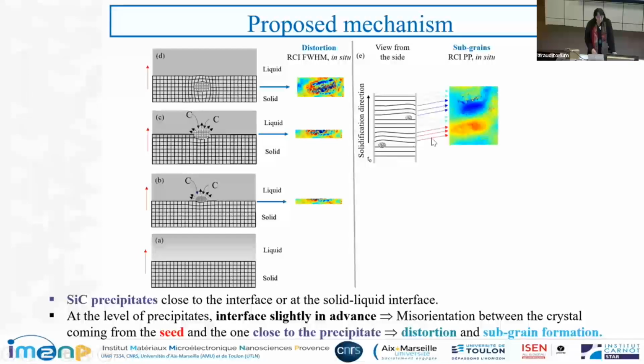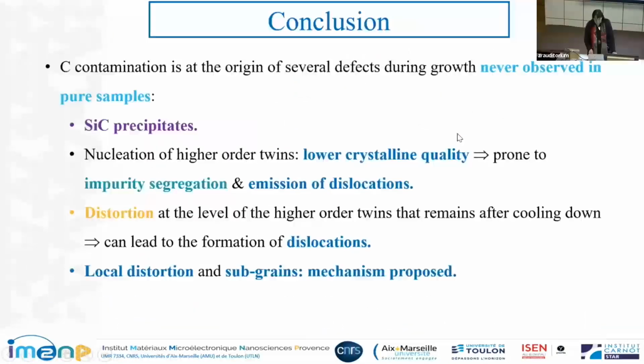subgrains or local misorientation. So as a conclusion, when carbon contaminates silicon during solidification, you have the formation of silicon carbide precipitates, but also the nucleation of higher order twins.